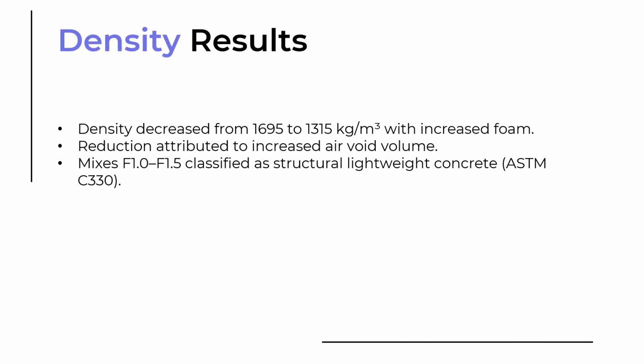For our results, we found that density decreased from 1695 to 1300 with an increase in the foam content. This reduction is attributed to the increase of air void volume. So mixes F1 to F1.5% of foam are classified as structural lightweight concrete. This is aligned with ASTM C330.